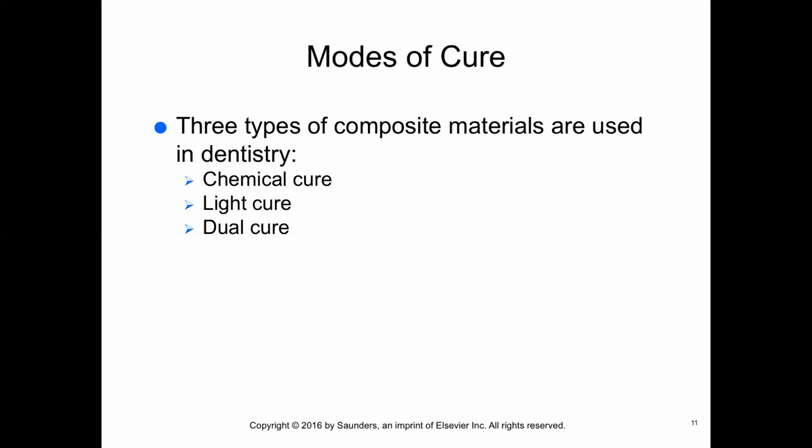When the materials are mixed together, it's important that they be spatulated to a homogeneous mixture to allow a thorough cure. If air is introduced during the mixing process, this may cause voids in the restoration.